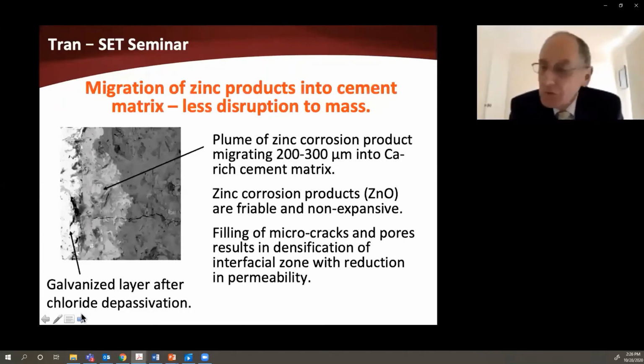The question then becomes, what happens when the zinc in concrete does depassivate? It will depassivate, of course, when you get very high chloride levels coming through. And what we found in laboratory studies, but also from a number of field investigations, is that when the zinc starts to dissolve from the free zinc area on the surface of a hot-dip galvanized bar, and that's the galvanized layer here that's been affected by chlorides and has depassivated, the corrosion products that form, which are primarily things like zinc oxide, actually migrate out into the adjacent cement matrix. There's a sand cement matrix out here. And what we found is that this is often of the order of 200 to 300 microns and even further, that the zinc corrosion products migrate into the concrete mass.